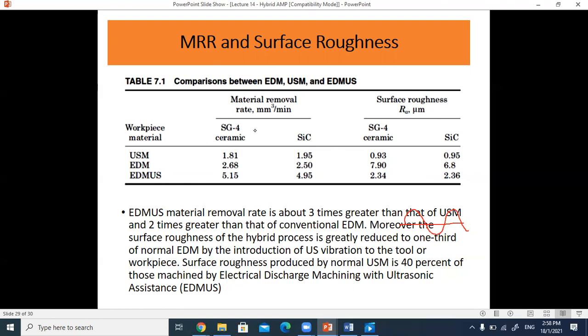which is SG-4 ceramic or SiC, we're looking at the material removal and surface roughness. In terms of material removal, you can see quite consistently that the ultrasonic EDM process is much better compared to the EDM or USM process. And comparing EDM and USM, EDM has a better material removal rate compared to USM. However, when you talk about surface roughness, surface finish, then USM performs much better.